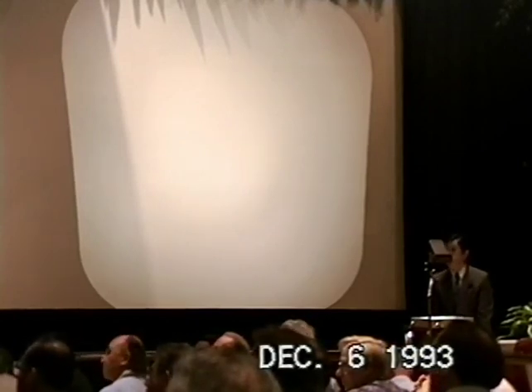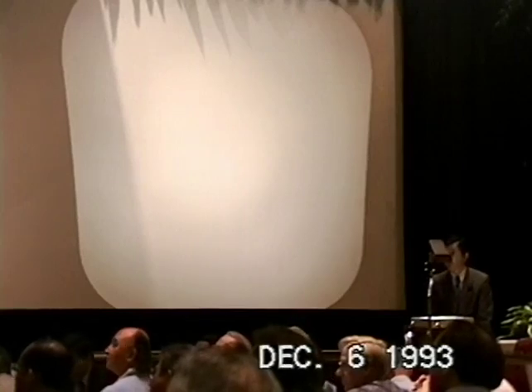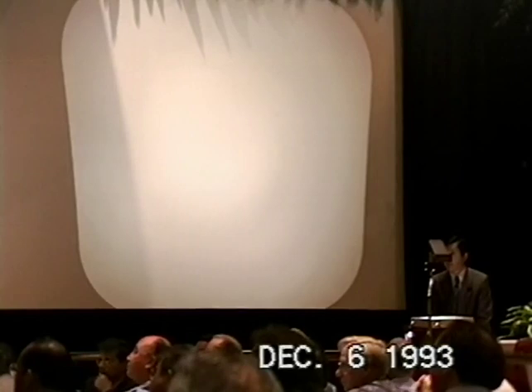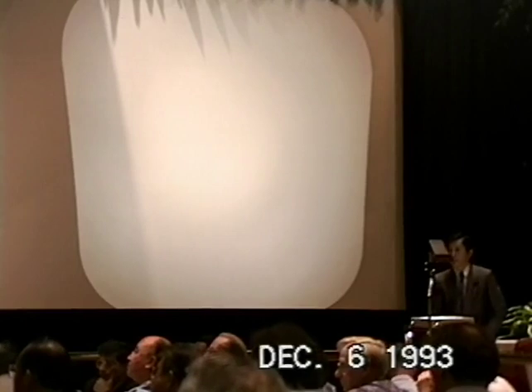I'd like to suggest that an interpretation of your dependence on DPD can be given something like this. As you go up past round about 0.65 and approximately 0.83 or 0.85, you begin to get a certain amount of internal damage. And I'll show in my paper this is so. A certain amount of internal damage gives you increasing numbers of dislocations, of which the absorption of hydrogen deuterium is particularly strong, giving you deuterium to combine with, which doesn't have a Coulomb barrier, just isn't charged.